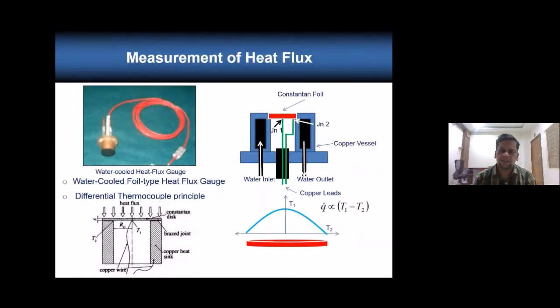Now coming to heat flux. Heat flux is measured with a Gardon type water cooled heat flux gauge. Its construction is very simple. This is also based on a differential thermocouple principle. I can show you here. This is a copper vessel. The front face is completely coated with a high emissivity paint, in the order of 0.95 to 0.98 emissivity value.